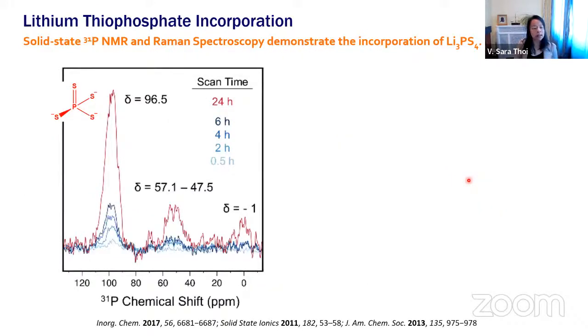We've also done solid state phosphorus NMR to show that indeed we have a material that's completely thiolated, this phosphorus, but over time our rotor does leak a little bit of air, but it does give us confirmation that this fully thiolated phosphorus does indeed start to hydrolyze over long periods of time inside the NMR spectrometer.